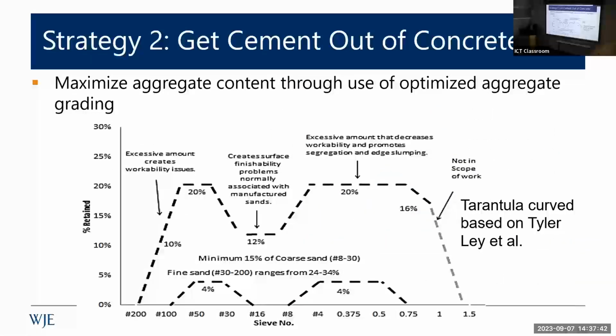The second strategy is even simpler. We just need to optimize our concrete mixes more. And since there are a lot of asphalt people, the concrete people are trying to take a page from the asphalt industry and basically create similar gradations using 3 or 4 aggregate bins, not just a coarse and a fine, and optimizing. And this is called a tarantula curve, because the person who invented this, Tyler Ley at Oklahoma State University, this looks like a tarantula. And this is just one tool of many.